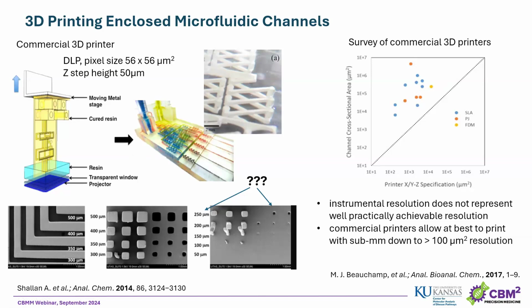What's actually interesting, though, is that one of the groups did a survey of the commercial 3D printers, and they noticed that even if the 3D printer manufacturers say that, let's say, our Z resolution is only 25 micrometers, or our laser spot size is 25, which would make the voxel size 25 by 25 by 25 micrometers, that's in reality never true, right? So they ran the survey of different commercial printers and showed the instrumental resolution does not represent well the practically achievable resolution, and that the commercial printers allowed at best to print sub-millimeter, maybe down to 100 micrometer square size resolution channels, right? So this is a significant limitation if you want to go well below that.